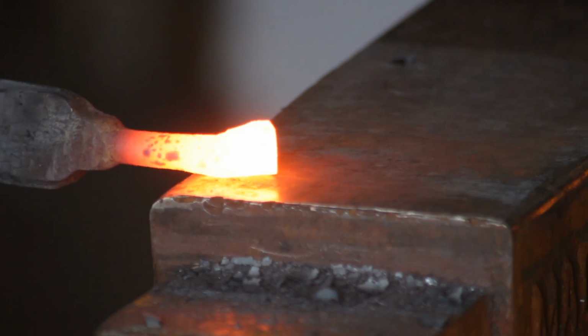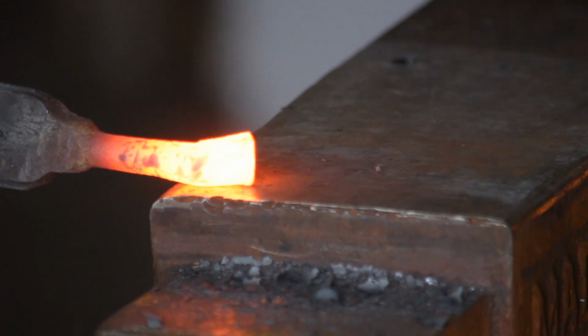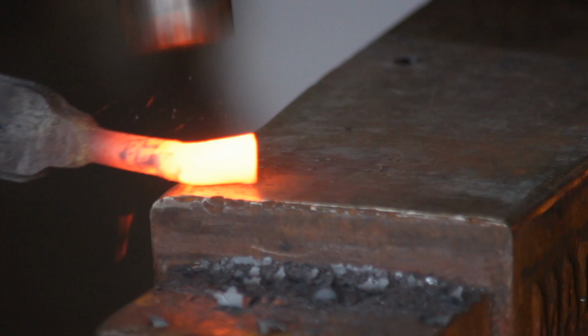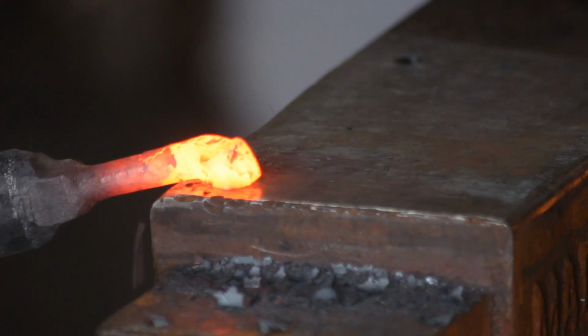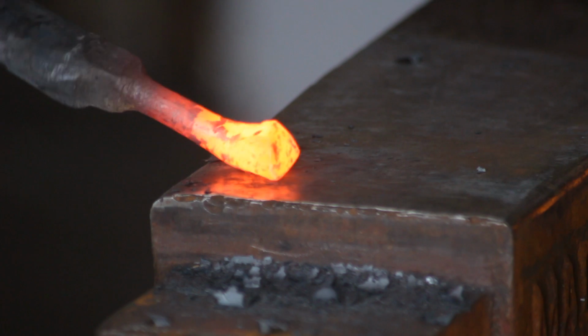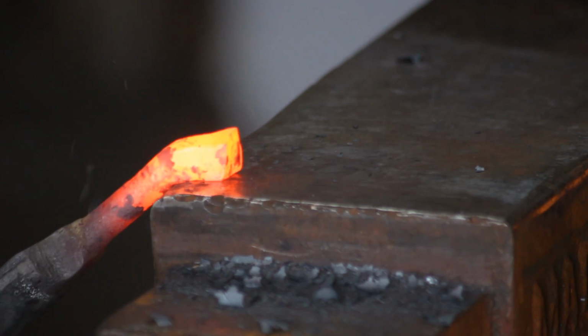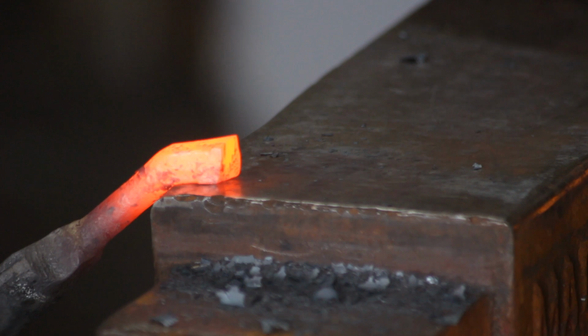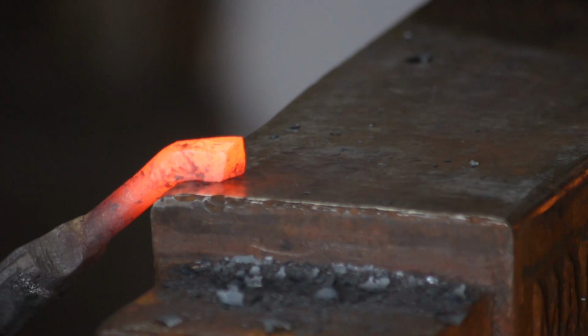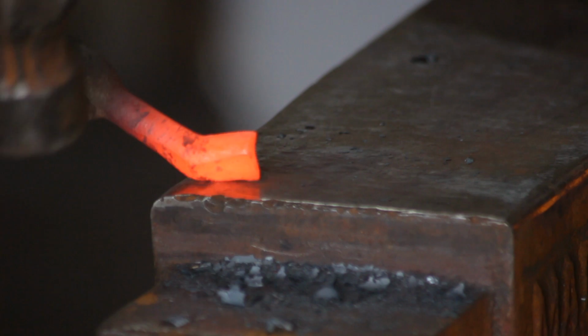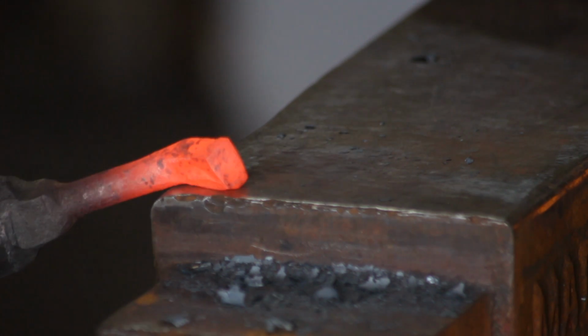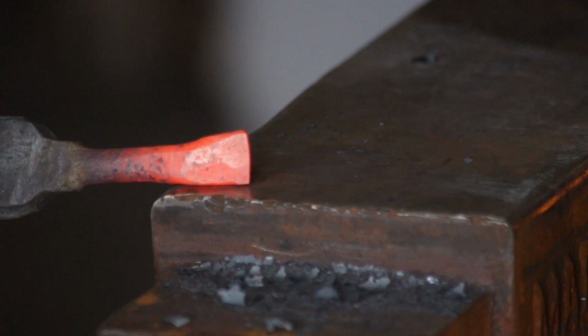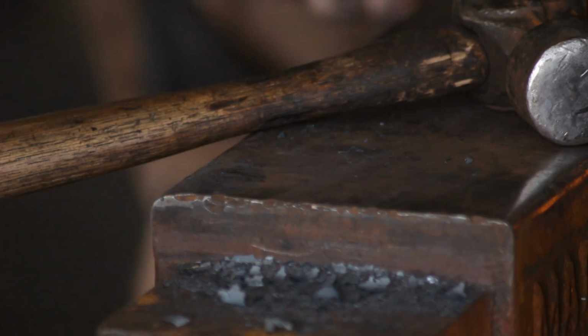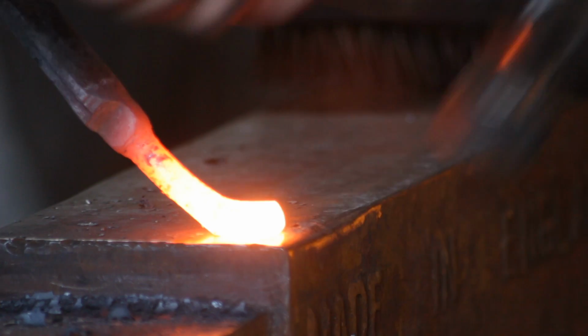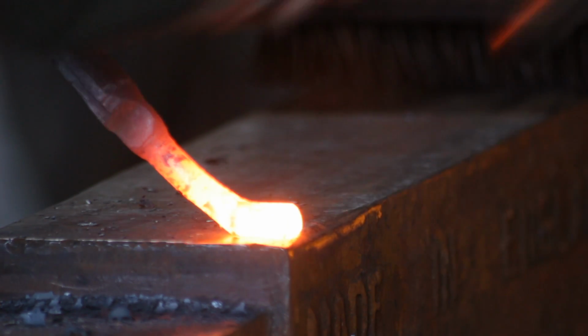So at that stage I will put my scarfing lines. You want to avoid any shearing planes, you want welding planes, so I'm tapering it towards the top of the scarf, and then coming onto the underside of the scarf to just flatten and spread out that material on the bottom side, and that helps contribute towards creating a welding plane. As you can see, this is now a trapezius shape. So then the final thing you can do is just stick a taper on the end, like you see in traditional scarves.